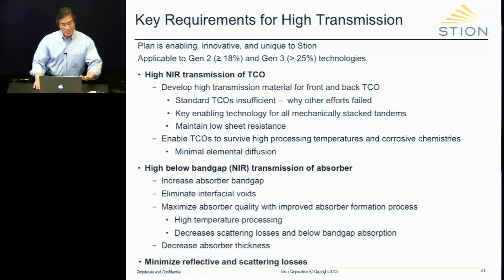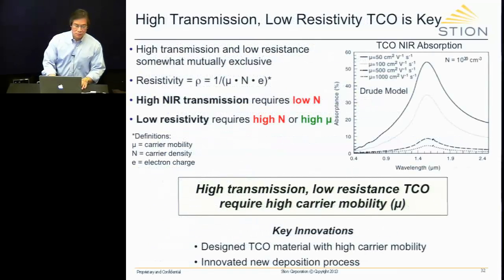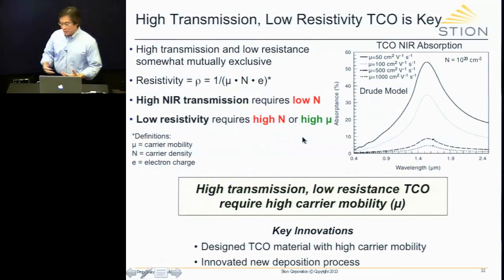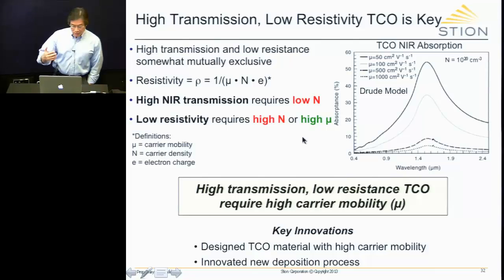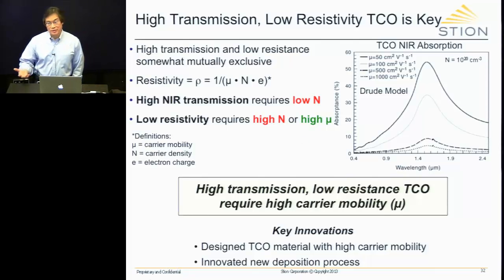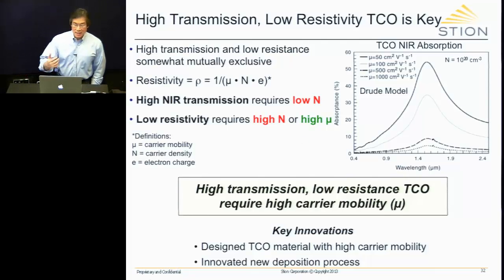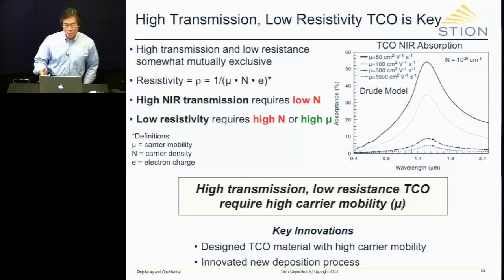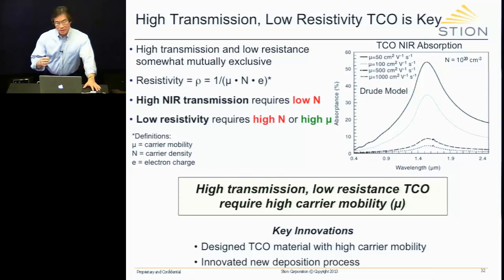So let me go through some of them here. First thing is, probably the most interesting problem, the TC, the transparent conductor, or in our case, we use a TCO. It has to be highly transmissive in the near infrared, and it has to be lowly resistive, or highly conductive. So why is this a problem? Well, because in order to be highly conductive or have low resistivity, you have to have a large carrier density, right? But the large carrier density results in an enormous amount of free carrier absorption.